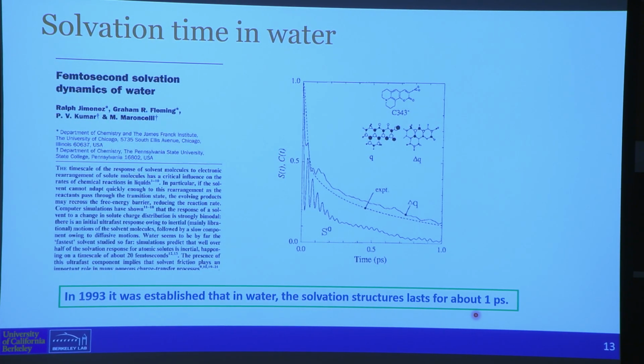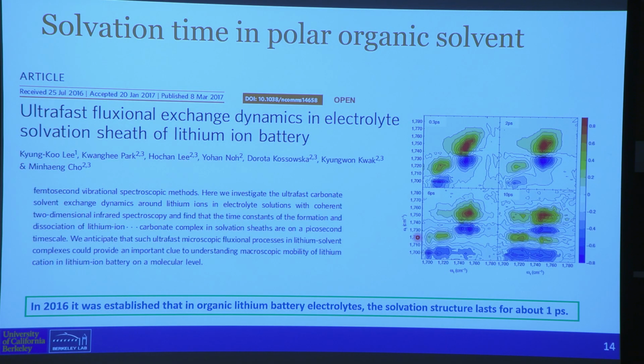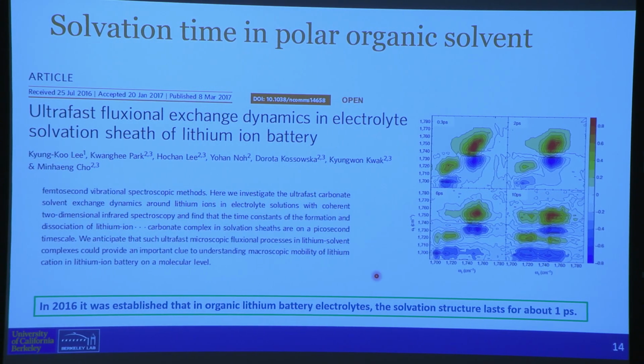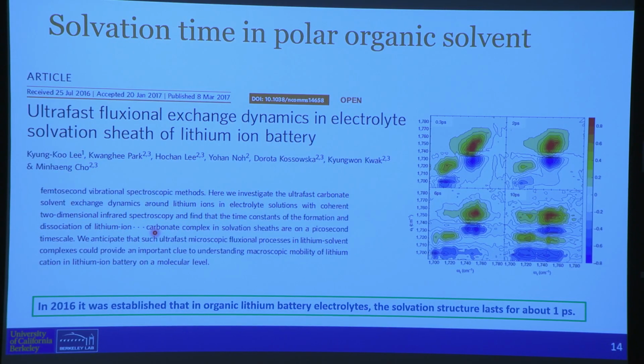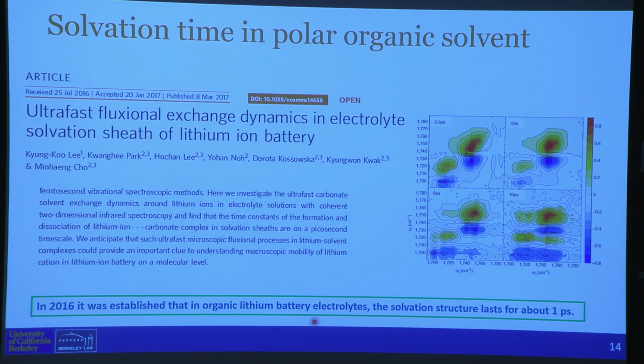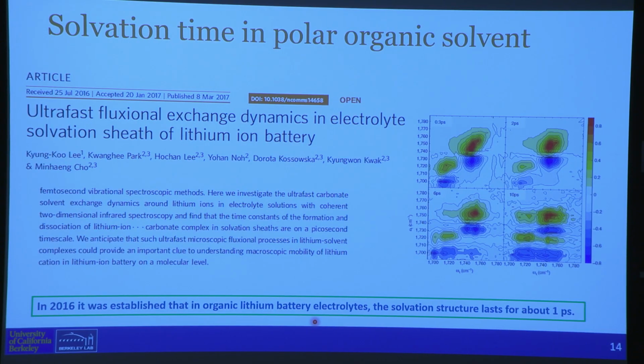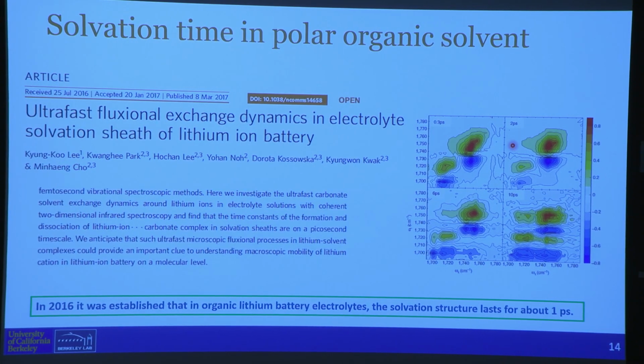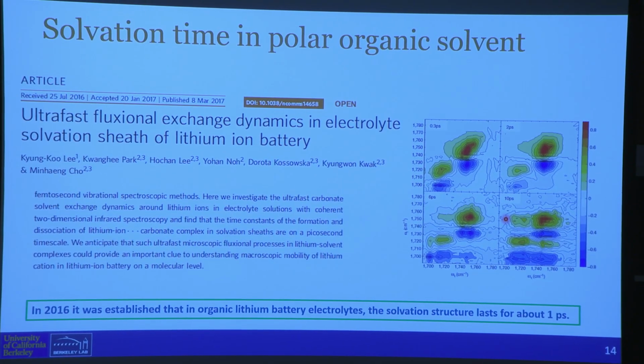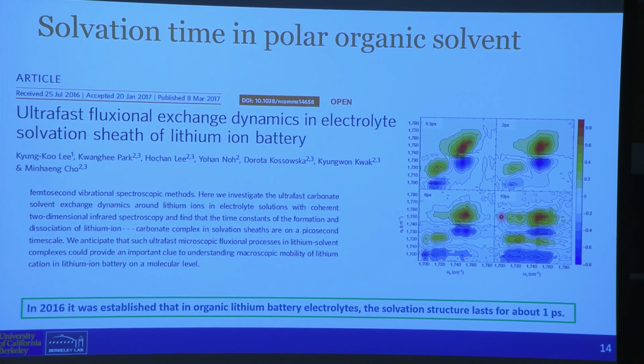They also have molecular dynamics simulations showing that this is true. And it doesn't matter what the details are. This is a structure factor or some complicated sort of thing that enabled 2D IR. But you can see that the time is picoseconds, and you can see the experiment and theory agreeing. Then in 2017, one of his students, Minhaeng Cho, not surprisingly, showed that, in fact, lithium ion in carbonates, this is the solvent you carry in your pockets, also has a solvation time of 1 picosecond, based on 2D IR data that look like this. If you understand this data, you understand more about 2D NMR than me. Okay? But that's the answer.